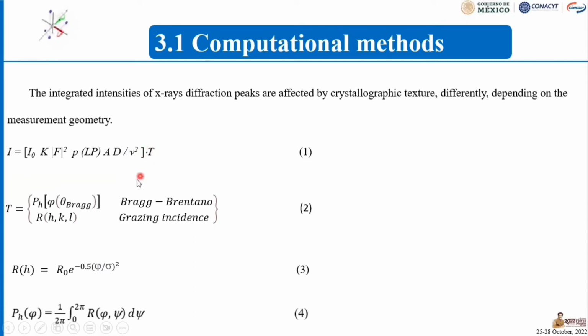So we have the different configurations here, in Bragg-Brentano and also in grazing incidence. In grazing incidence, the modulating factor is the corresponding direct pole figure evaluated at the Bragg angle. The model applied in this work consists of a Gaussian-shaped inverse pole figure, and further calculations on the dependence are being considered.